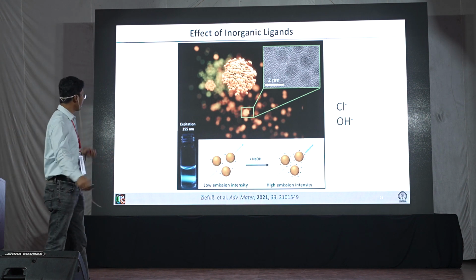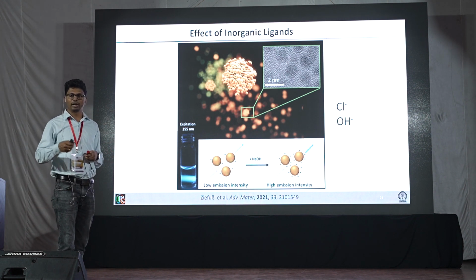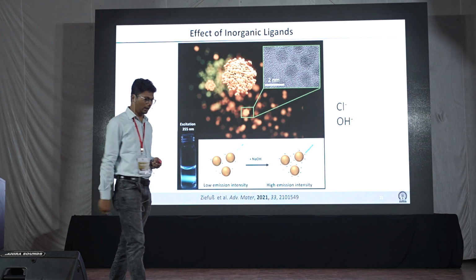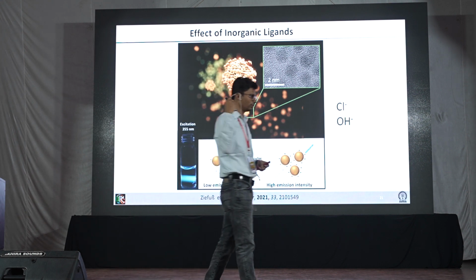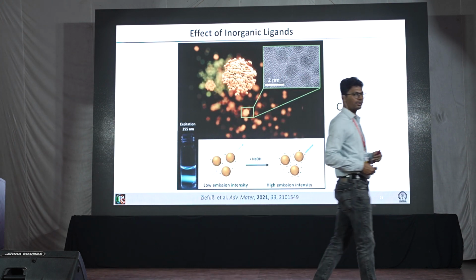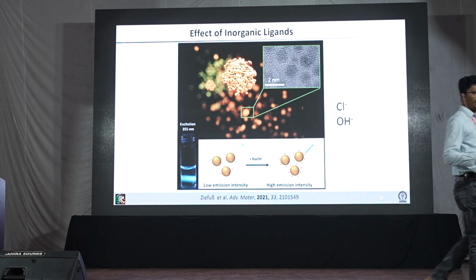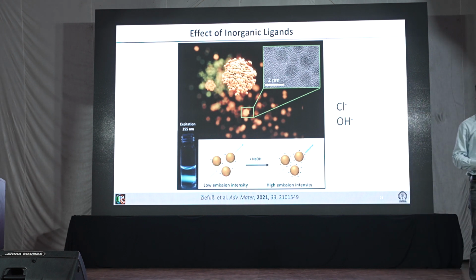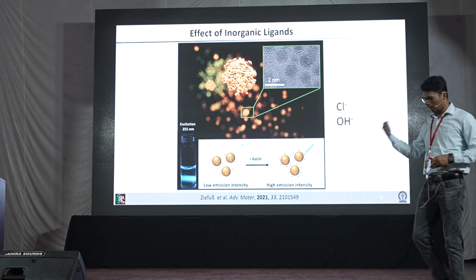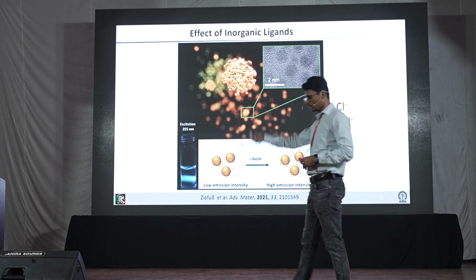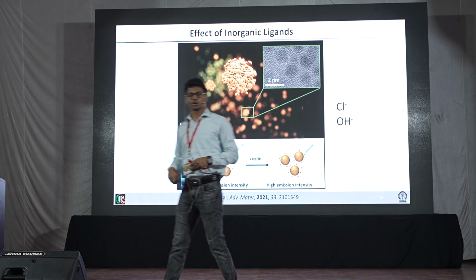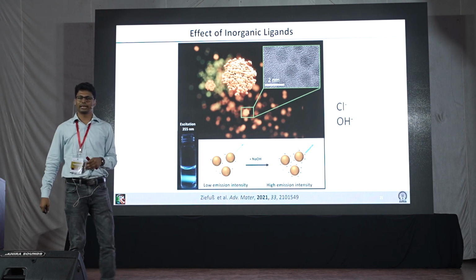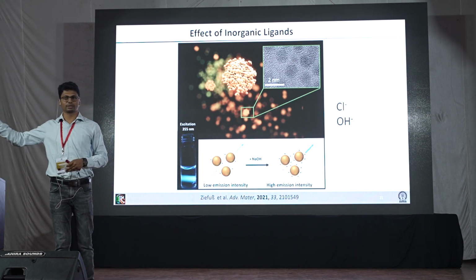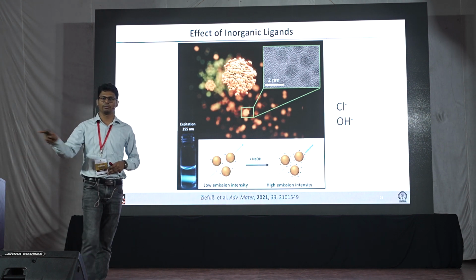Where you create clusters using gold foil, first you create bigger nanoparticles, then you do another laser ablation process to break them down to a small size, and you have only inorganic ions there, chloride, Cl minus, OH minus in your solution. You can change the ions. There also, we saw that the clusters are luminescent. So that gives a clear indication that not just the ligand is important for the origin of the cluster's luminescence.